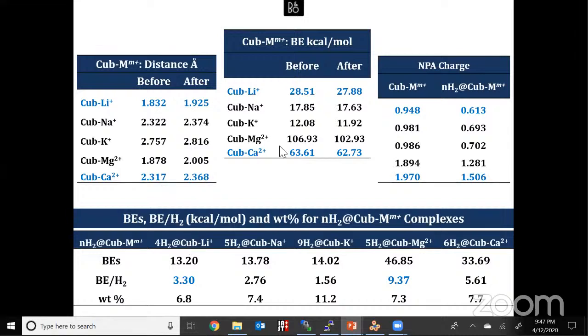We figured out why. We calculated the bond distance of the metal atom before and after hydrogen binding. The difference is not that much, just a little bit. And we calculated the charge of the metal ion before and after hydrogen binding. There is a charge transfer taking place. You can see the metal charge is 0.948 before hydrogen binding. After hydrogen binding, it is 0.613.